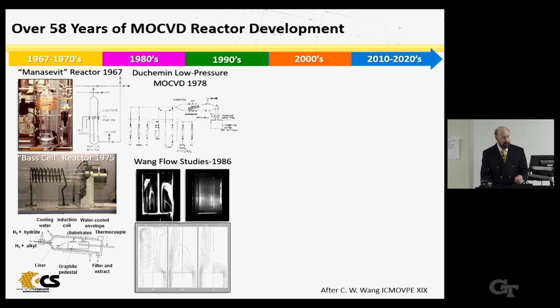Another important event occurred in around 1986 or so when Christine Wong and her co-workers at MIT Lincoln Laboratory did the first detailed flow studies of vertical stagnation point flow reactors, as shown here. They did both simulations and experimental work showing that you could develop beautiful, perfect laminar flow in a low-pressure MOCVD reactor under certain conditions of temperature and pressure and rotation rate. So this opened people's eyes to the fact that we have control over the gas phase, pressures, chemistry, surface concentrations to be able to do very large area uniform epitaxy.